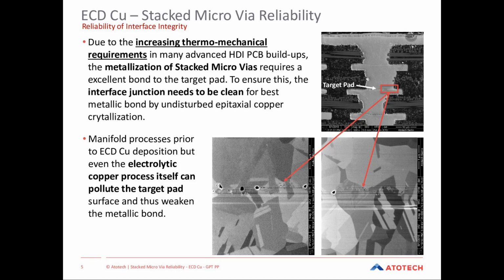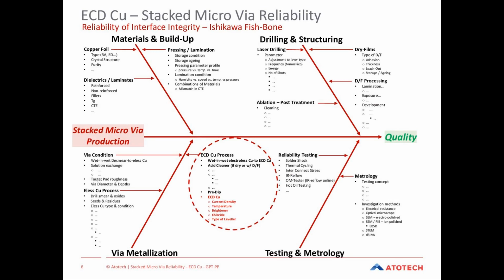Is pretreatment prior to ECD copper important for the interface reliability? What has to be considered? Yes, we did not cover this today, but it is a part of our troubleshooting approach in general. If you look at the fishbone we have discussed today, you will see that there are several very important things to consider when you do pre-treatment of your boards. On one hand, it is always important to have a very good wetting of the microvia and the target pad. Of course, you also want to remove some dirt remaining from other processes in this area. For example, even electroless copper deposits sometimes are not perfectly rinsed inside the microvia, and then you want to remove alkaline residues from the electroless copper process.